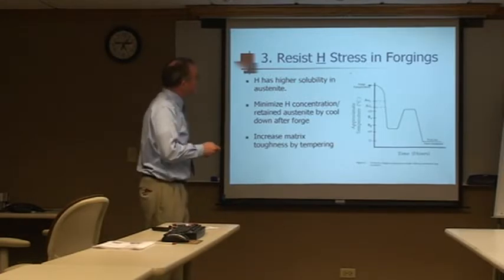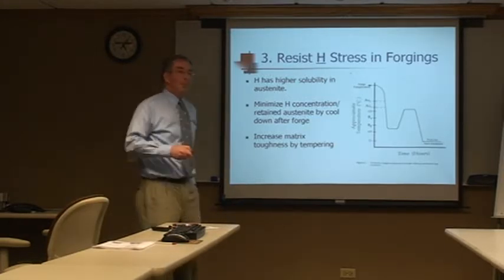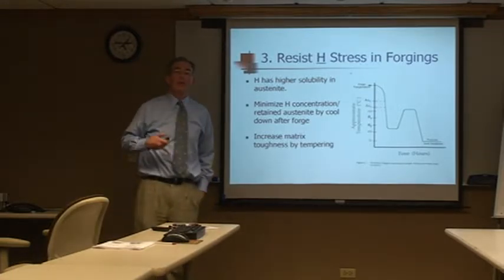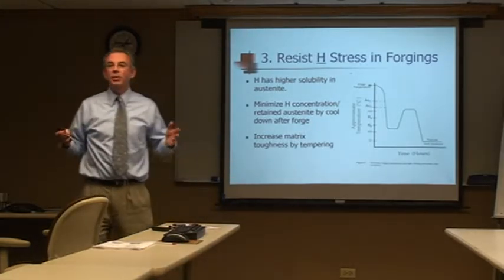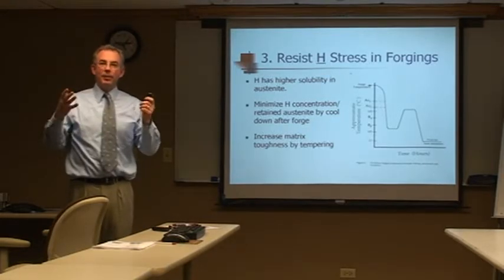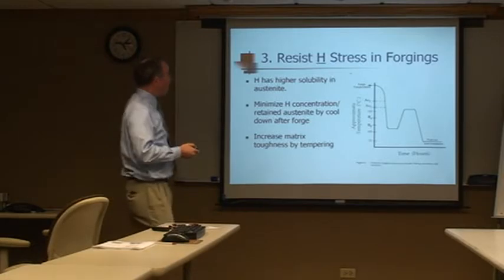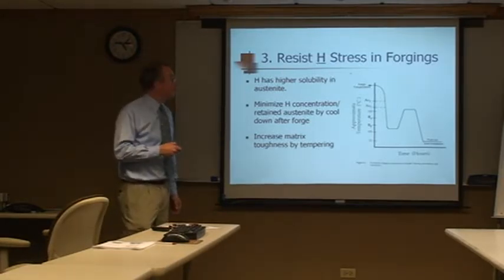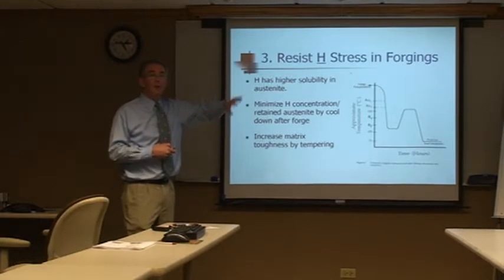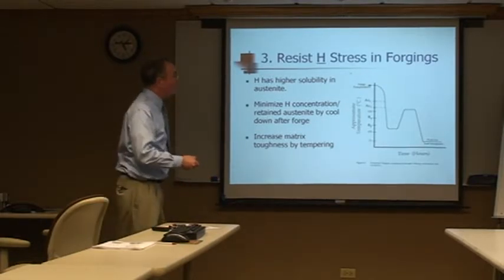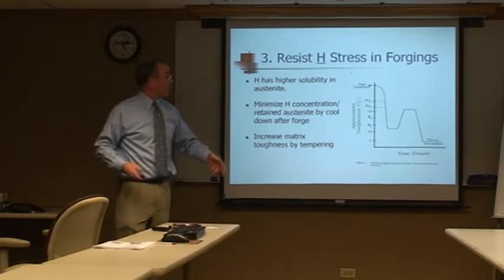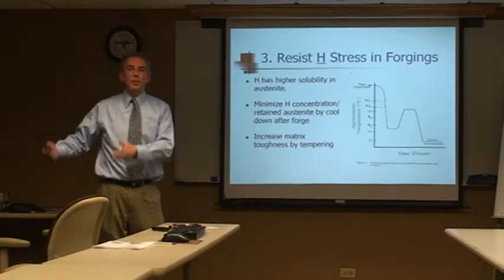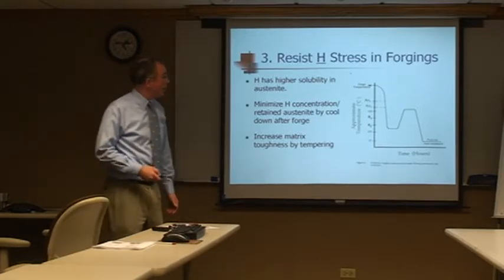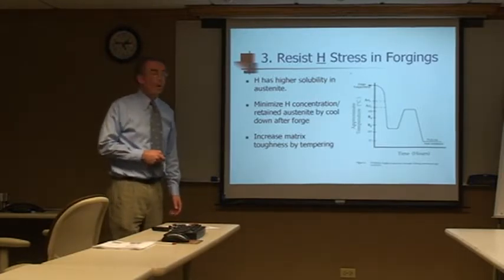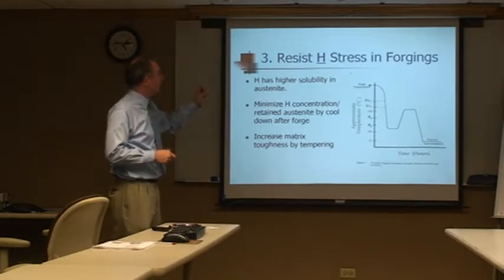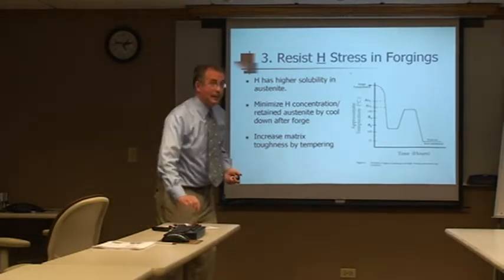The reason this cool down is so important is because some grades, especially nickel bearing grades, microstructurally, if you were to slow cool those, you could end up with a phase called retained austenite. When we're up here at forge temperature, above 1600 degrees, the microstructure is predominantly austenite. When we cool down, we end up with ferrite, pearlite. Maybe if we cool fast enough, we create a phase called martensite or bainite, harder phases. But some grades are sluggish to transform, so if we slow cool, you can end up with these islands of retained austenite.